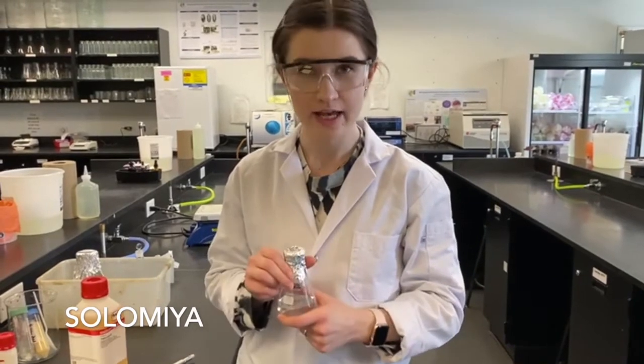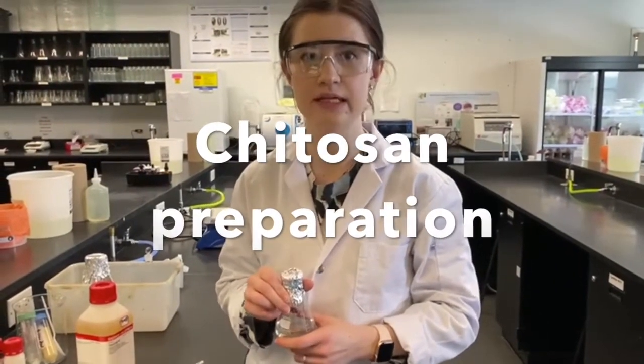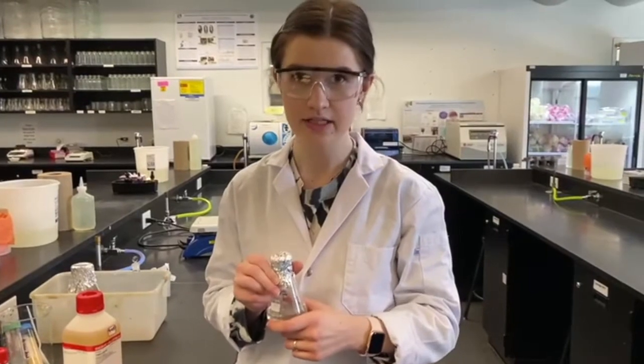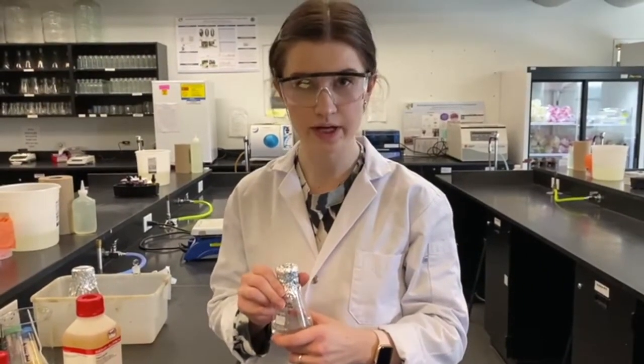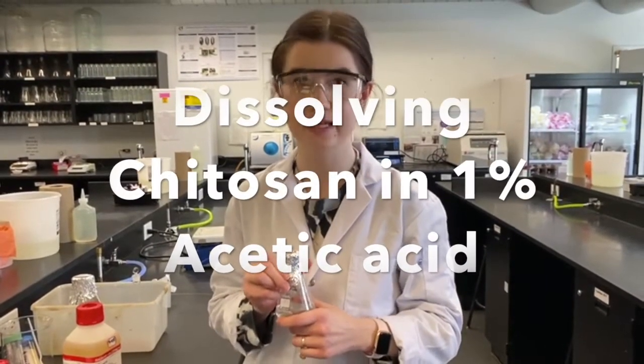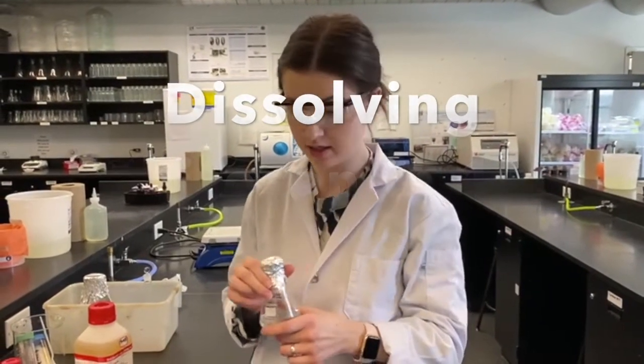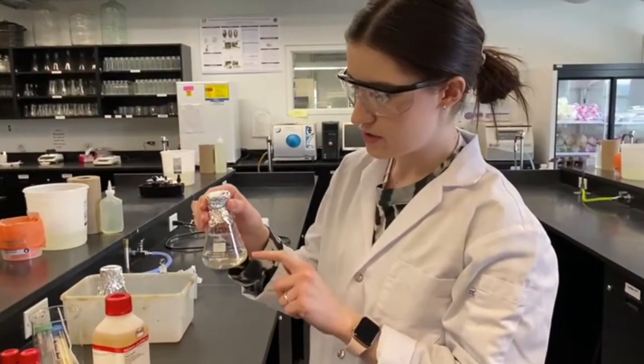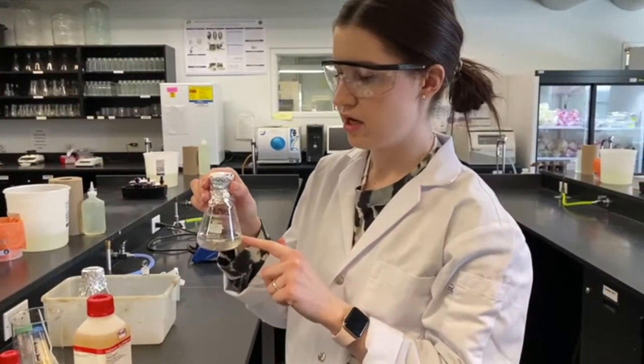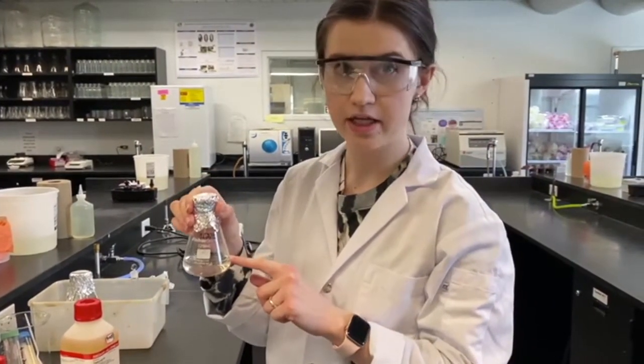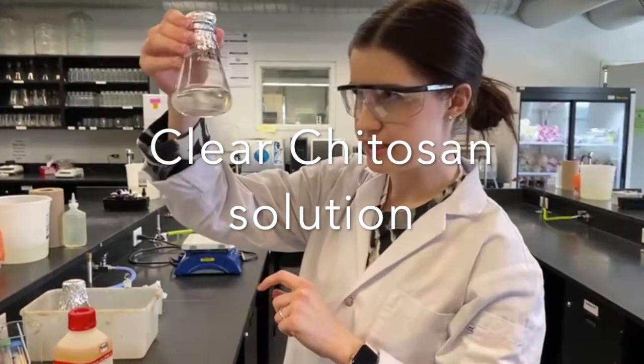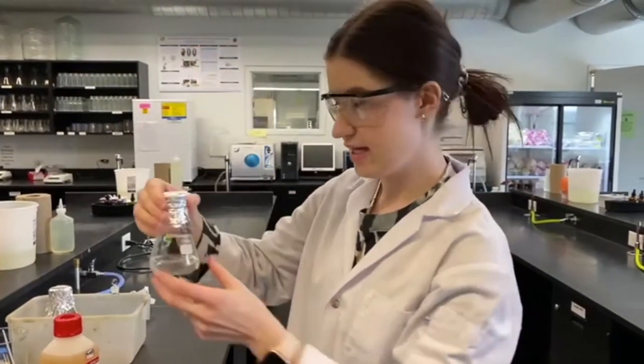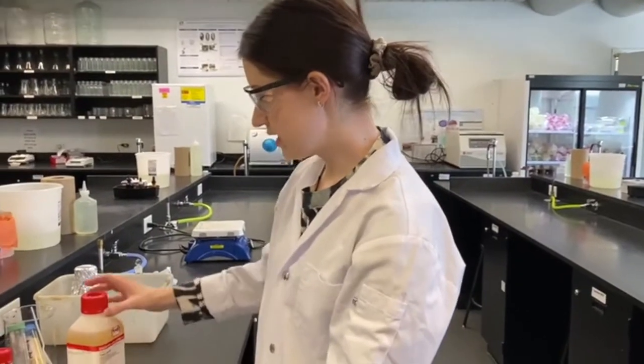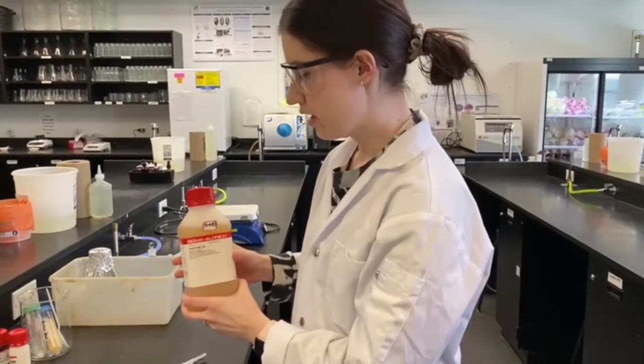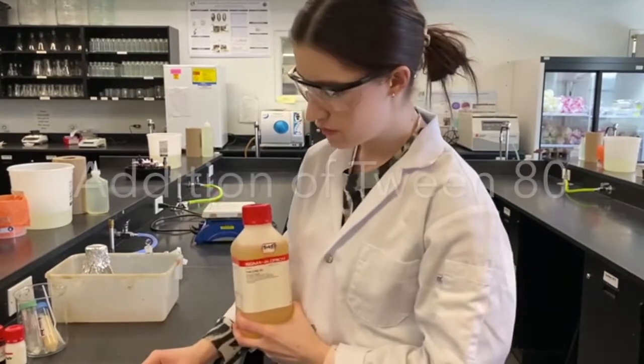So the first step in preparing nanoparticles is making a solution of chitosan. Chitosan is not soluble in water, that's why we are dissolving it in acetic acid, 1% acetic acid. So this is the solution that was kept overnight, and it was stirring overnight, so we can see it really clear and nice. And now we will be adding Tween 80 to bring all of the components together and to make it more uniform.